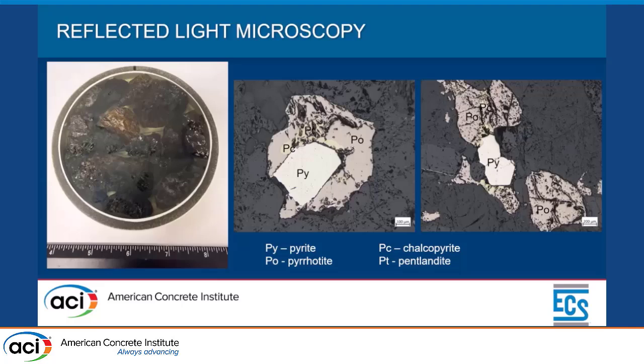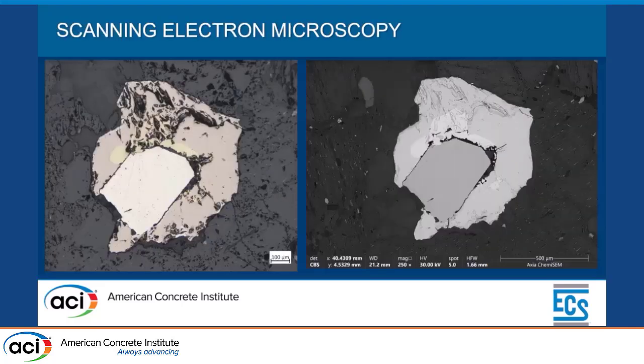So the pyrite is a yellowish white color. It has a weak anisotropy. Pyrrhotite is really strongly anisotropic. It has more of that creamy brown. The pyrrhotite is more the creamy color with a little bit of pinkish to it, and we commonly see this pitting with the pyrrhotite, because it is softer. The pyrrhotite's really going to have a higher relief. But anyway, this is the gold standard for looking at iron sulfides and identifying them.